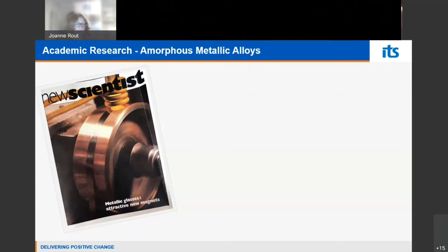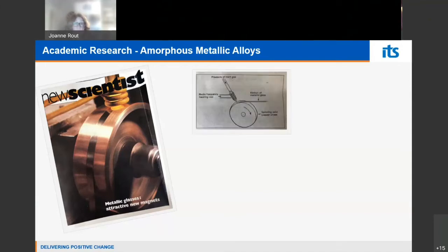These are alloys that, if you cool them very quickly before they can crystallize, you freeze in the structure of the melt. So it's an amorphous, non-crystalline structure. And why might that be interesting? We'll come on to that. But I actually made these materials myself in the lab. You basically take the alloy and induction heat it in a quartz tube with a small hole in the bottom, a nozzle. Once it melts, it flows down through the nozzle and lands on a very fast spinning copper disc, which withdraws heat quickly away from the thin ribbon of metallic glass, and there are no crystals in there. It's a random structure of atoms.